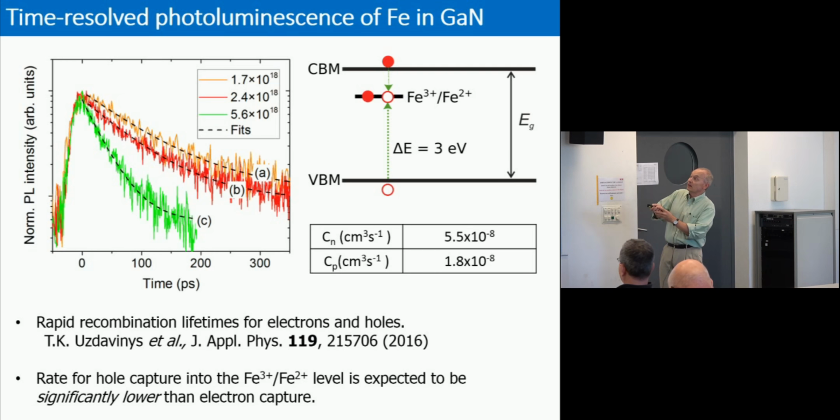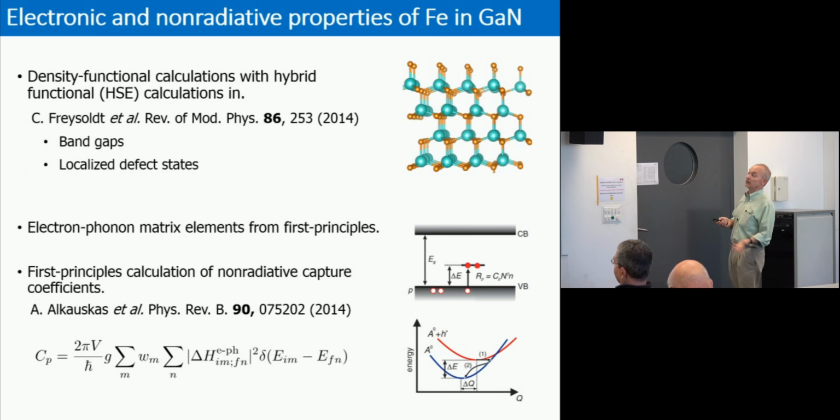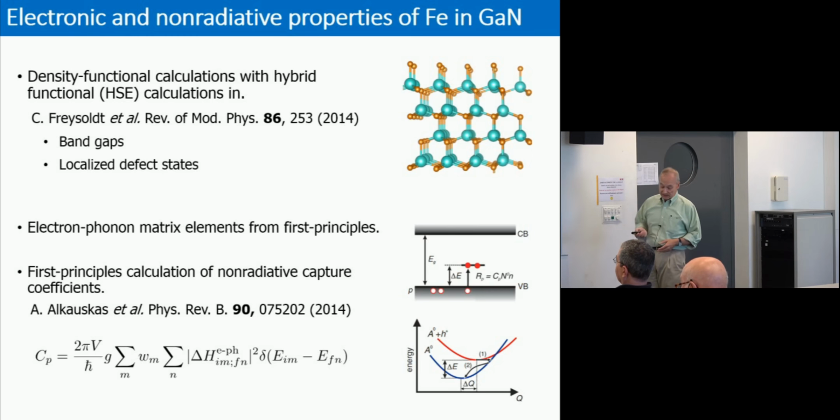And the answer basically is that this consideration of a single level associated with iron and focusing on where it is in the band gap, it's too simple. It's a simple rule of thumb that is not good enough to describe all cases. And in particular, what you need to do for the case of iron is to take excited states into account.